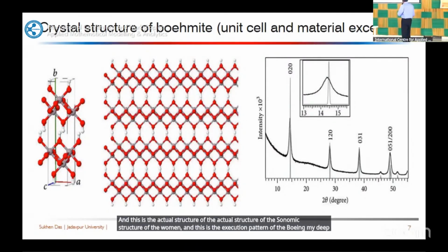And this is the actual crystallographic structure of the Boehmite. And this is the X-ray diffraction pattern of the Boehmite. If these peaks are there, then you can easily tell that the material is nothing but Boehmite. And the intensity and the position, the 2 theta angle, are very important for the property of the material.